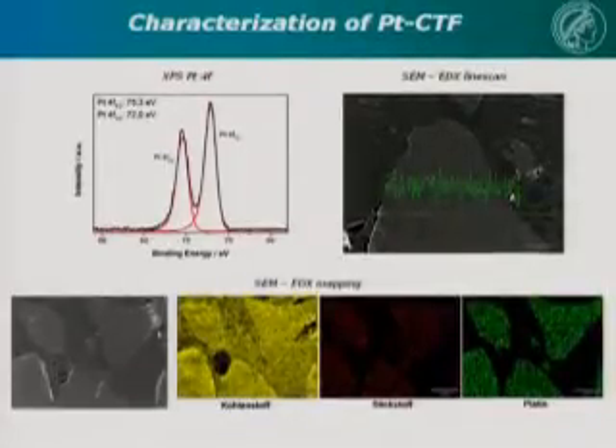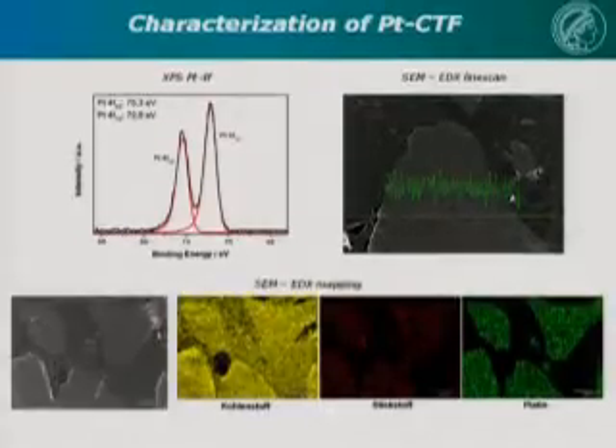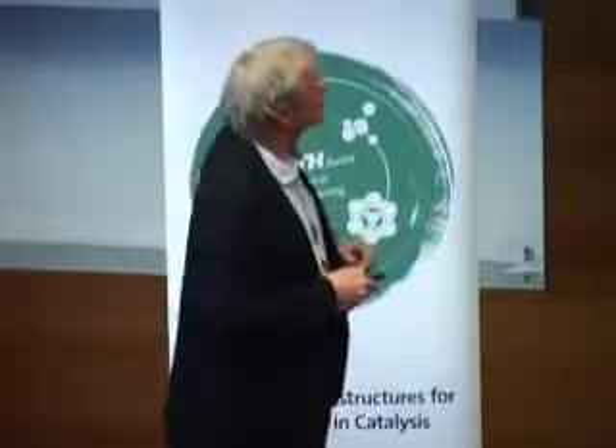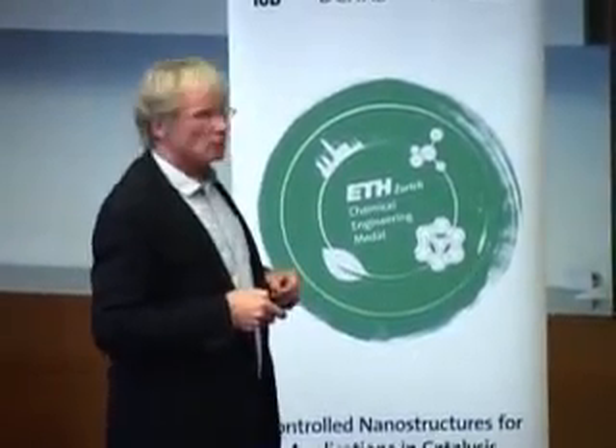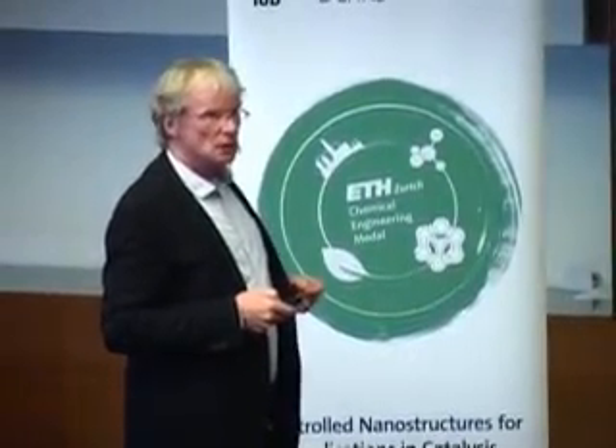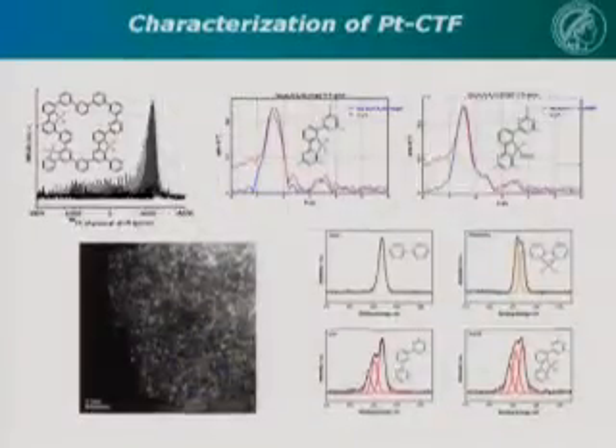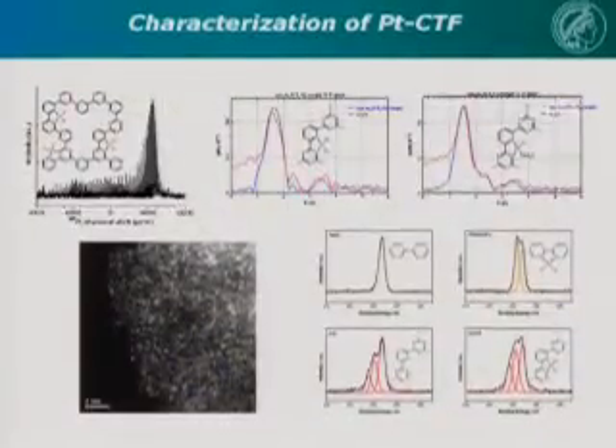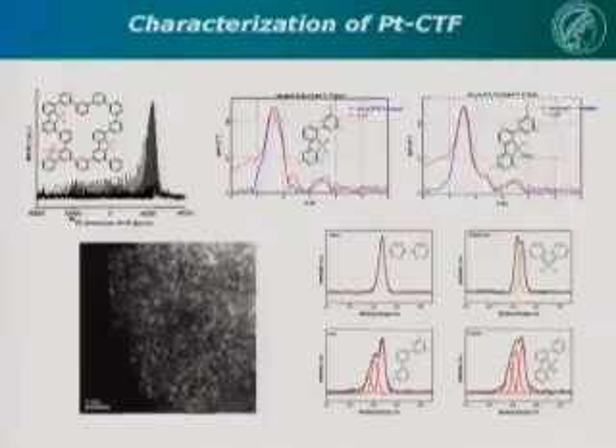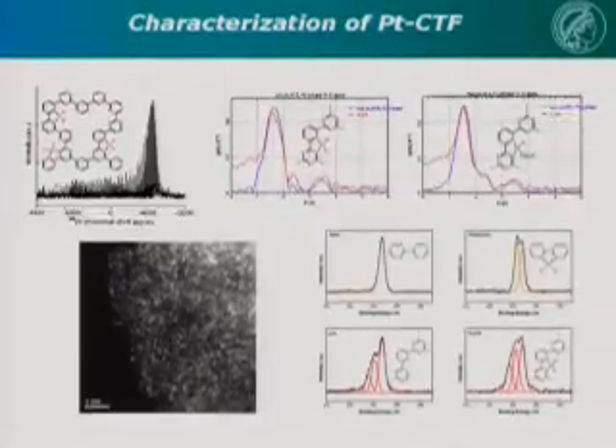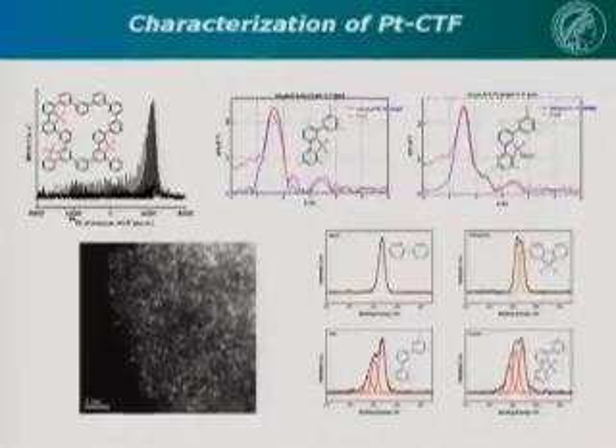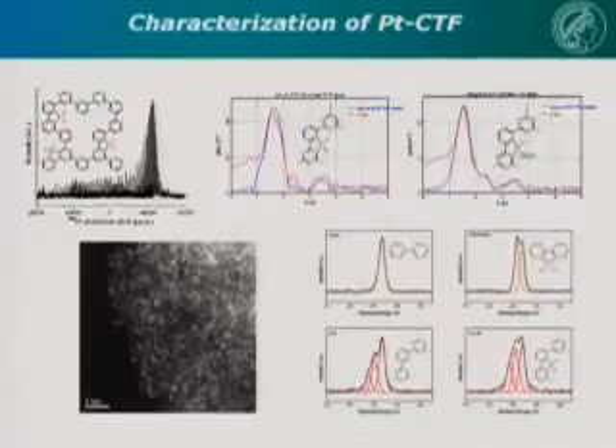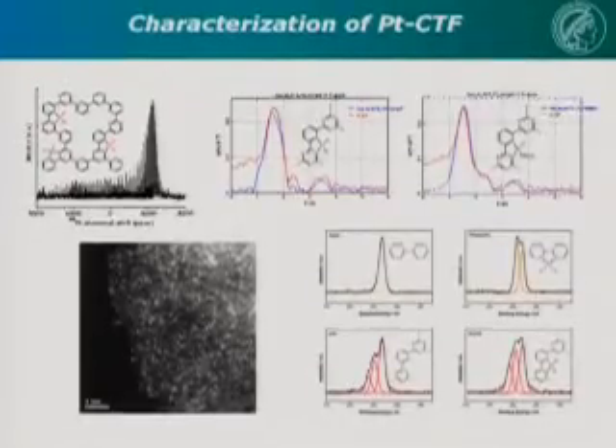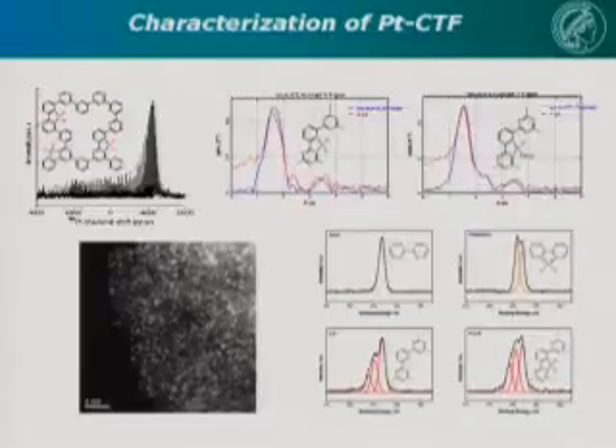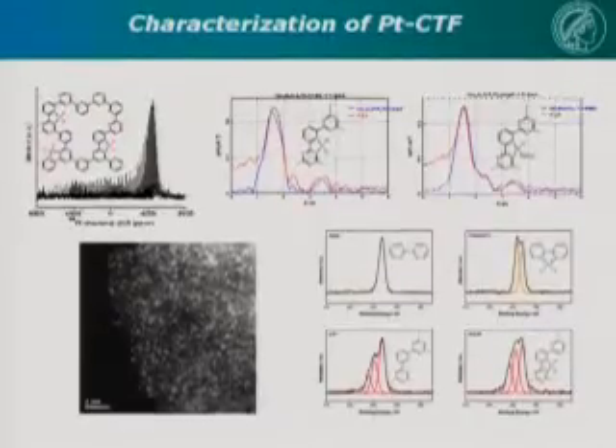So the platinum is really homogeneously distributed over this covalent triazine framework. It's basically platinum-2 in the system as analyzed by XPS. This is a 2 nanometer scale bar, so this is aberration-corrected high angle annular dark field STEM. Each of these dots is actually a single platinum atom. So it's atomic dispersion of platinum in this covalent framework.